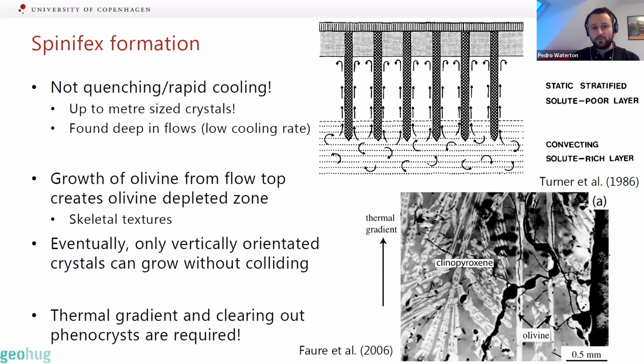How do spinifex form? Well, the most important thing is that it's not quenching or rapid cooling. And I think this is really commonly mistaken. Again, thinking about the scale, to get crystals up to a meter in size, this cannot be happening through very rapid crystallization. It takes a while to grow crystals this big. It's also important to note that you do find platy spinifex quite deep into flows where the cooling rate should be pretty low, on the order of a degree per hour or somewhere in that ballpark.